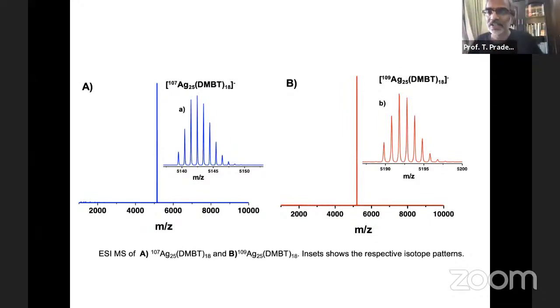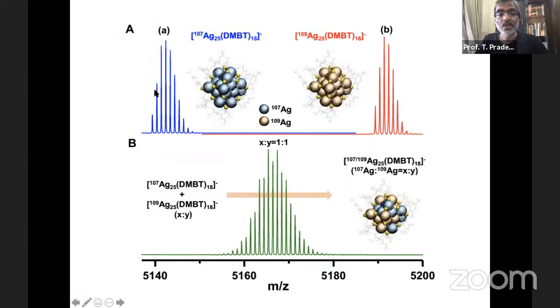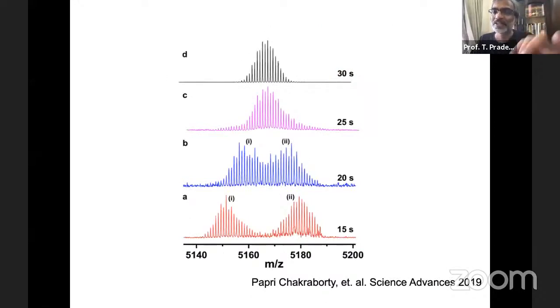Of course, it is not 100% isotopic purity, it is 99.9 or 99.5% or so. So you have that, and you mix these two. So when you have this and you have this, this is what you had initially. You mix it together, you see that suddenly you get only this and these are completely lost. So you get isotopic mixing, and this is something that you can study in a time-dependent fashion, but it is so fast that initially just in 15 seconds, you measure one mass spectrum, in 20 seconds, at 25 and 30 seconds, this whole thing is gone. It means that the chemical exchange is very similar to something that happens between H2O and D2O.